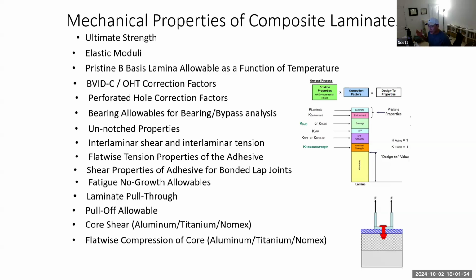Perforated hole correction factors, kind of discussed that. The pre-cured skin, the flow skin side, is perforated for acoustic attenuation. So we need to understand what the knockdown factors are when we do that to the laminate. Unnotched properties, basically meaning a pure, pristine laminate without any defects, without any holes. Interlaminar shear, interlaminar tension. What is the capability between the plies, along the matrix, in shear and tension? Flatwise tension properties of the adhesive. Sometimes we need to know what the tension capability of the adhesive is between the face sheet and the core. Shear properties of the adhesive for bonded lap joints.